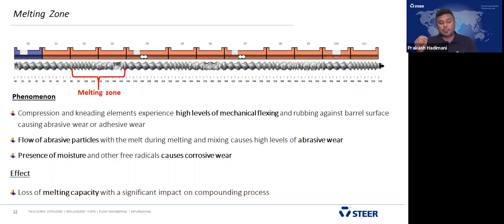The flow of abrasive particles with the melt during melting and mixing contributes to melting and mixing, but it also causes a high level of abrasive wear. There is also the presence of moisture, because some hygroscopic materials like polyamide, and some of the fillers, are hygroscopic in nature and absorb moisture. The presence of moisture and free radicals causes corrosion.